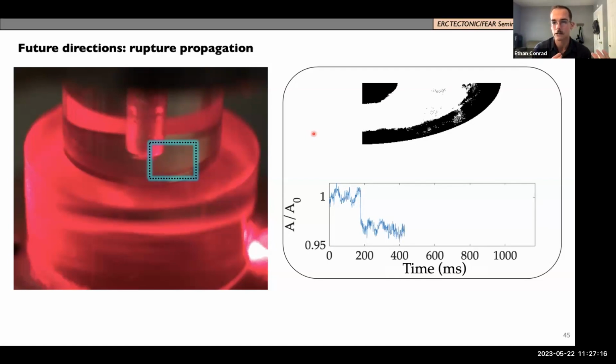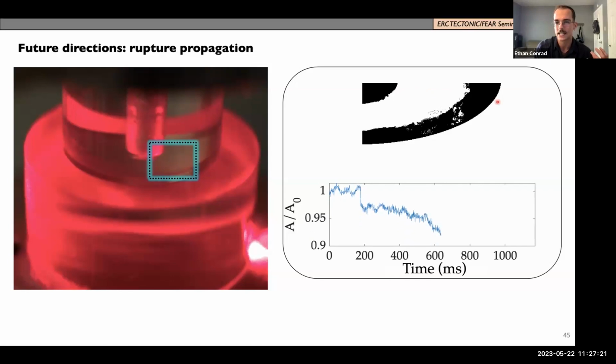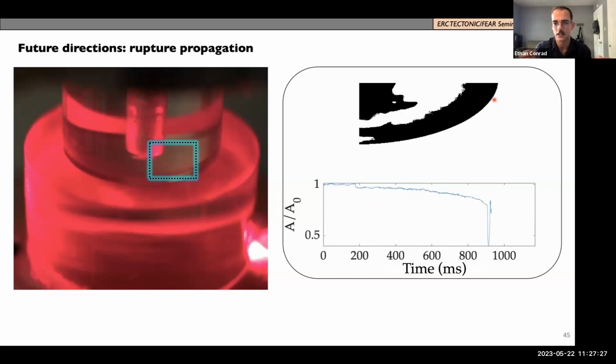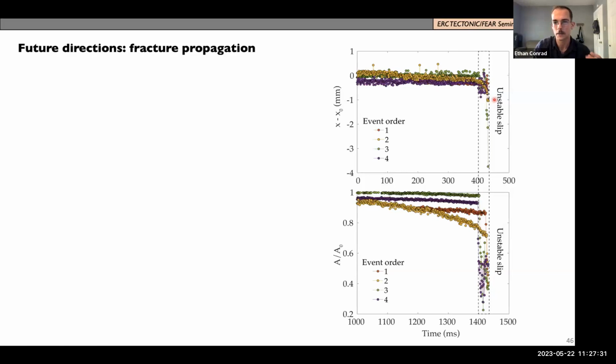And so that's exactly what we're seeing here. On top, white is the melt patch, black is the pristine interface, or things that aren't the melt patch, and we'll see the shrinking, and we can see it in the curve of that melt patch, and then final breaking. Here are some plots from different events. The order just means different events, kind of a confusing term. Yellow and orange and purple and green are separate events.